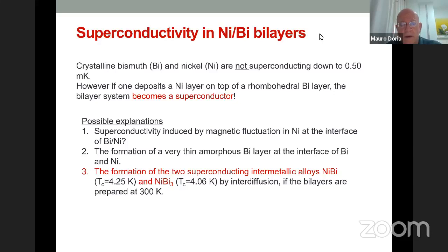But bismuth is a very interesting and complicated element because amorphous bismuth can be superconductor. And there are always stories about bismuth having a very high, even room temperature, superconductivity, but this is usually amorphous bismuth, that is a mystic word. Nickel is magnetic, it's not superconducting. And nevertheless, it was found that if you deposit nickel on bismuth or vice versa, this bilayer becomes superconductor.